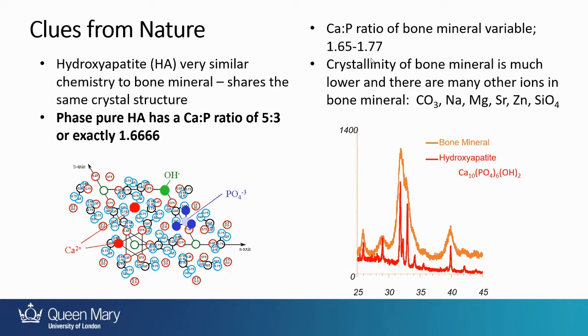And if you deviate from that ratio, you end up with the hydroxyapatite decomposing and producing what we call a biphasic or multiphasic material. So you end up with different calcium phosphates or calcium oxide in there as well. Bone mineral, on the other hand, is able to have calcium phosphate ratios that vary all over the place because it substitutes different ions into the crystal structure of hydroxyapatite. So, for instance, things like carbonate and silicate will substitute in for the phosphate groups within the structure, and sodium, magnesium, strontium, and zinc will substitute in for the calcium ions.